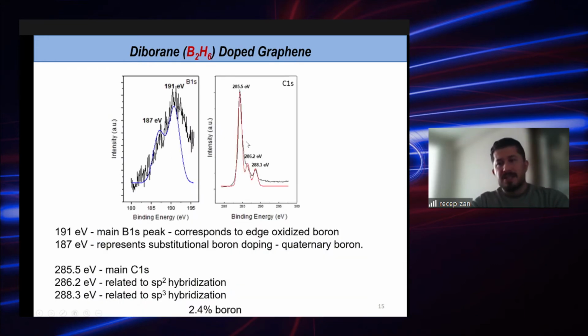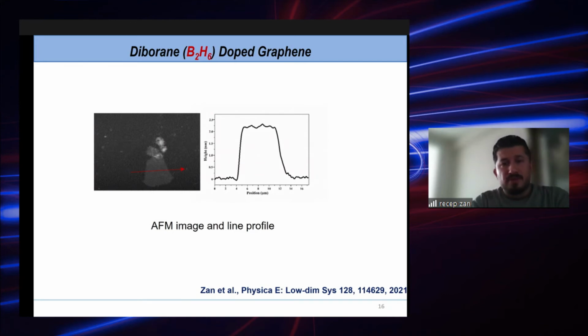But yes, we agree that we have something in the structure, but to make sure graphene is doped substitutionally with boron, we need to check, or we have checked, XPS measurements, X-ray photoelectron spectroscopy. So we look at the B1s and C1s spectra, I mean boron and carbon spectra, and let me talk about the boron side. As you see here, the 191 electron volt peak is the main boron peak, and more importantly, the 187 peak is the substitutional boron peak, which makes us sure that boron substitutes carbon in the structure. When we use 10 SCCM diborane, the boron content in the graphene structure was 2.4. We measured thickness using AFM and saw around 1.5 nanometer thickness, which is related to 1 or 2 layers.